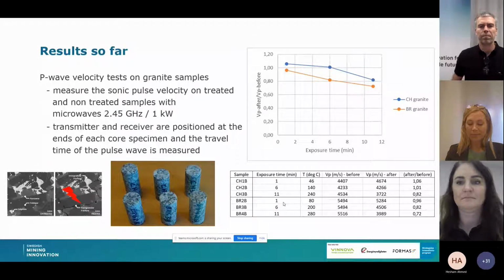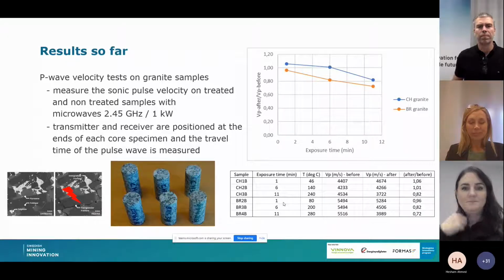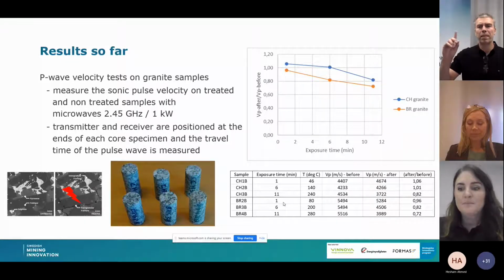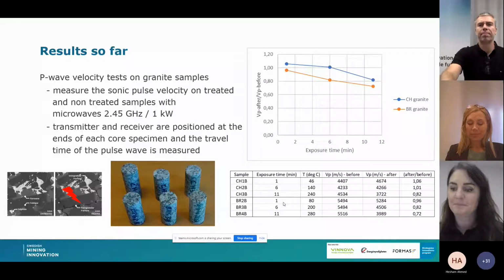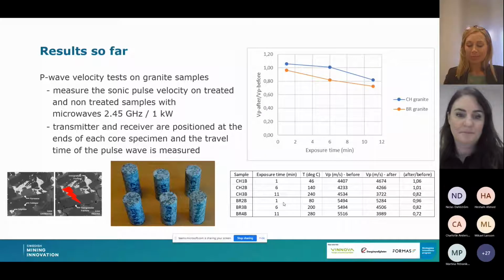So here are our first results. You see that after exposure with low power microwaves, we still see a decrease in the velocity of the sound in the rock samples. And this is explained by the fact that microwaves induce cracks. It's a proof that sound travels much slower after exposure with microwaves.